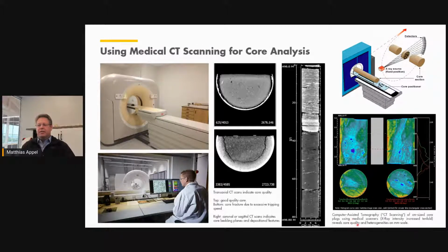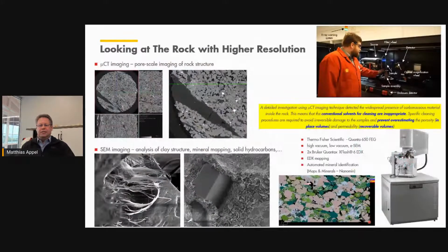The medical CT scanners give us a resolution typically on the millimeter scale, maybe 0.7 millimeters or so as a voxel resolution. That is not enough to see the individual pore structures. In order to do that, we are looking at the rock with a higher resolution, and that typically happens with micro CT scanners these days. You see an example here where one of my colleagues is just loading a sample. The sample is tiny now, and we talk about that a bit later. But instead of having an X-ray source and a detector rotating around the sample, we now have a millimeter-sized sample rotating in front of the X-ray source, so that the attenuated X-rays are then being amplified and going into a detector.